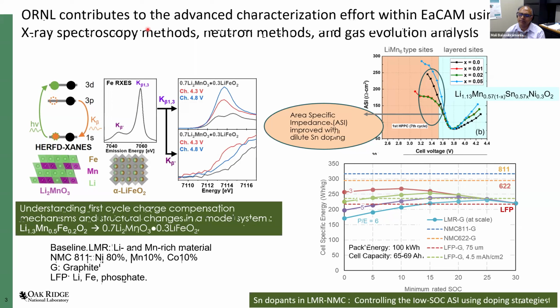So the idea is that if we can make materials out of these Earth crust abundant elements, we might be able to replace more expensive critical materials which contain nickel and cobalt. There is a clear need to get away from cobalt and perhaps also to reduce nickel. As you can see from this plot, where we are plotting the cell-specific energy versus a metric called the minimum rated state of charge, these lithium and manganese-rich materials show promise when compared to materials currently in use, such as nickel-based materials 811 and 622 or lithium iron phosphate. So we believe that if this material can be developed well, it can compete with LFP technology.